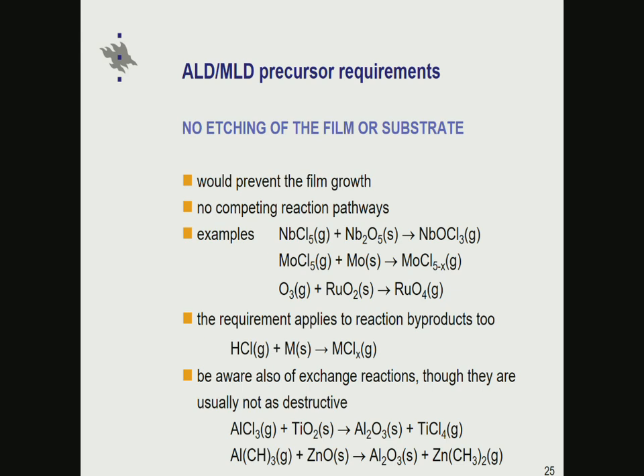There is actually, at the interface, a replacement reaction, so that when aluminum chloride comes over the titanium oxide, it replaces titanium in the oxide. Titanium now forms the volatile chloride, and aluminum oxide is deposited directly without reacting with water yet. But this is a self-terminating reaction, so that after 10 ALD cycles of aluminum oxide, this kind of exchange reaction no longer takes place. But it's important to know that it's possible, because that affects the control of the individual layer thicknesses in the case of nanolaminates. One gets a thicker layer of aluminum oxide than expected based on the cycle number, or if making a mixture of two metal oxides, there would be more aluminum oxide in the mixture than calculated based on the cycle numbers alone.